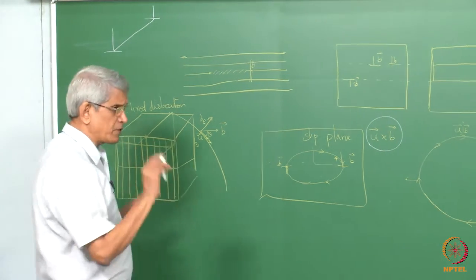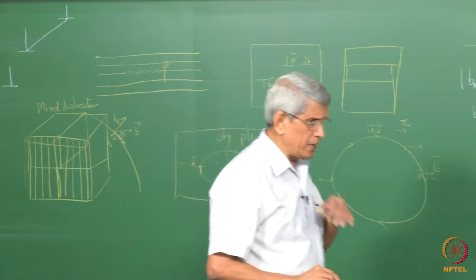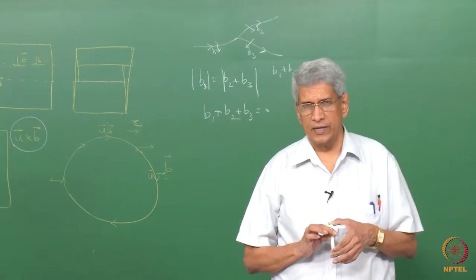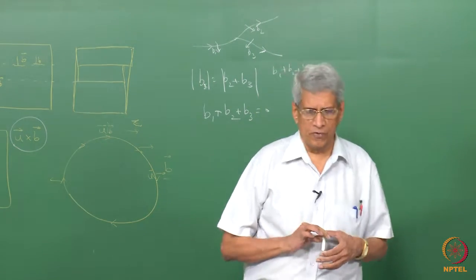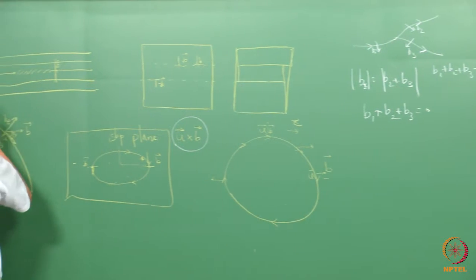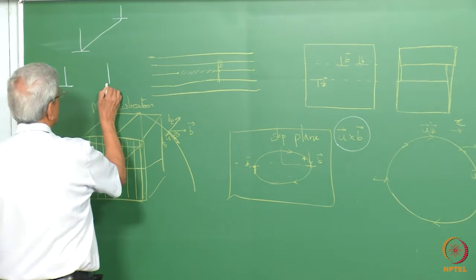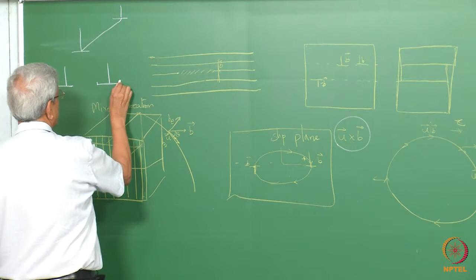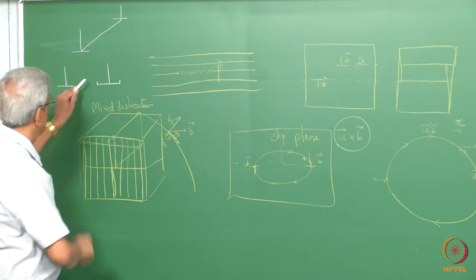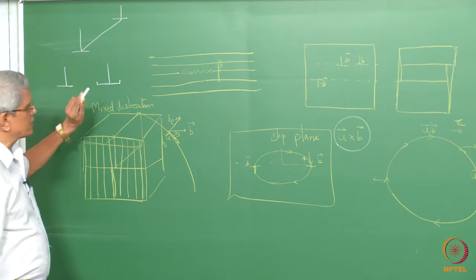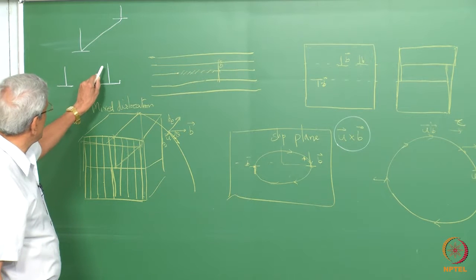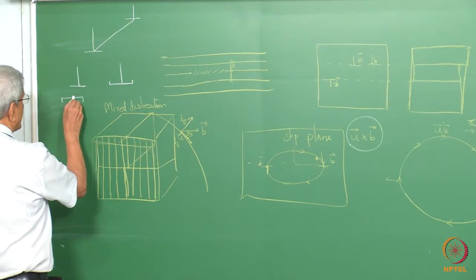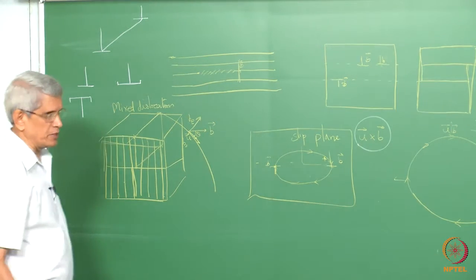This represents a general dislocation; it does not distinguish between a screw dislocation and an edge dislocation. But in the book by Hirth and Lothe, Theory of Dislocations, the edge dislocation is defined by an inverted T, where the direction it points is where the extra plane is. If the extra plane is up, this is the way it will be shown. This symbol is used for an edge dislocation.